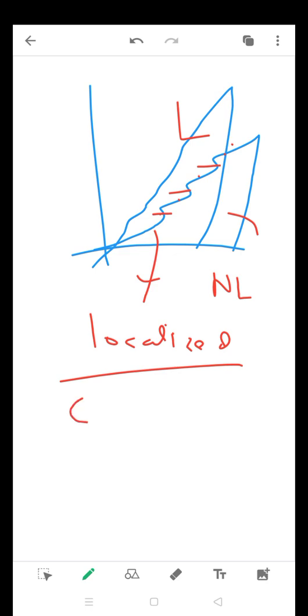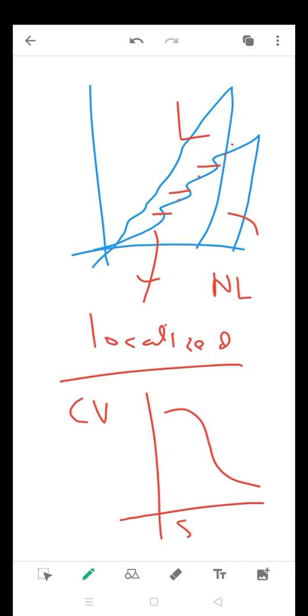So when we did the cyclic voltammetry test, we found that the area with respect to the scan rate was higher in the case of the layered samples, whereas much lower in the case of non-layered samples. So that gives the layered SSC more charge storage capacity compared to the non-layered SSC. So there is another aspect.